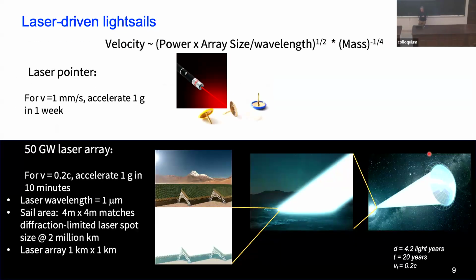So light, of course, imparts very little in the way of momentum. If you imagine pointing a laser, like my laser pointer here, at the screen, if I pointed this at something that had the mass of a thumbtack continuously for a week and the battery held up, I would be able to accelerate that thumbtack on a frictionless surface to about 1 millimeter per second. So that gives you an idea of the scale.